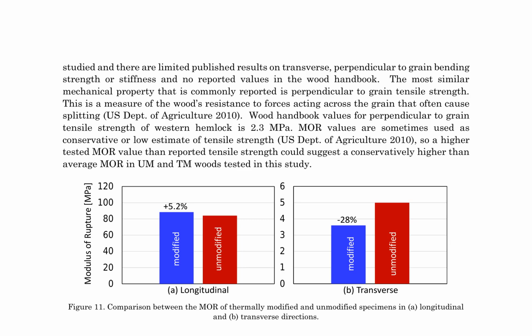This study focuses on the mechanical properties of thermally modified and unmodified western hemlock wood, specifically in terms of its modulus of rupture, MOR, and fracture energy. The MOR is a critical parameter that reflects the wood's resistance to bending forces and is influenced by grain orientation. The research reveals that the thermal modification process leads to a significant change in MOR for both longitudinal and transverse directions, with an increase of 5.2% and a decrease of 28%, respectively.